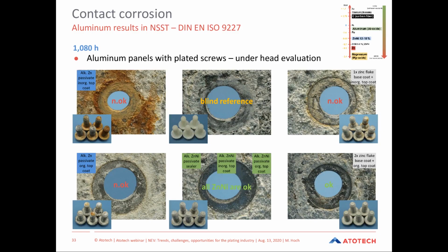After 1080 hours and under head evaluation, the result is even more clear. Zinc flake systems with organic top coats and in particular zinc nickel platings can pass the test. The clear recommendation for parts that come into contact with aluminium is therefore zinc nickel plated parts.